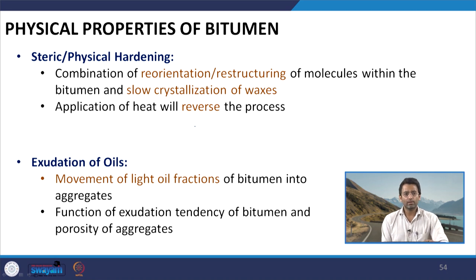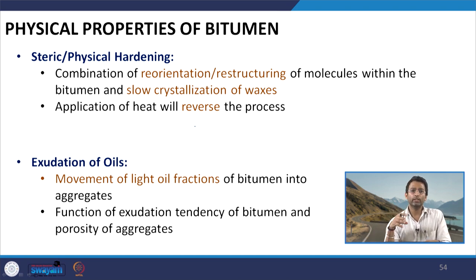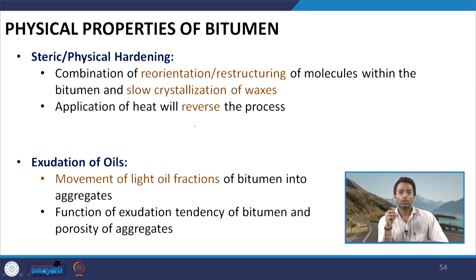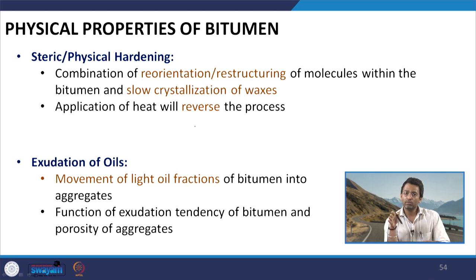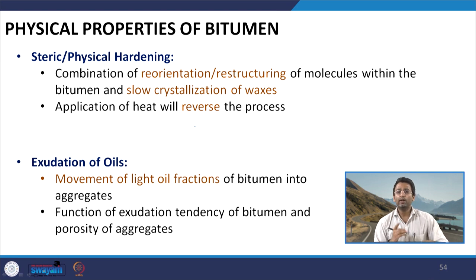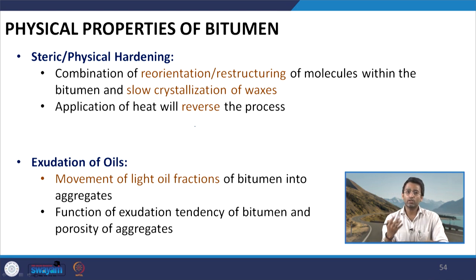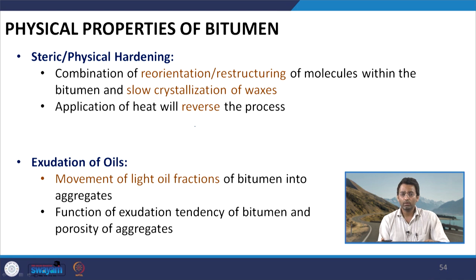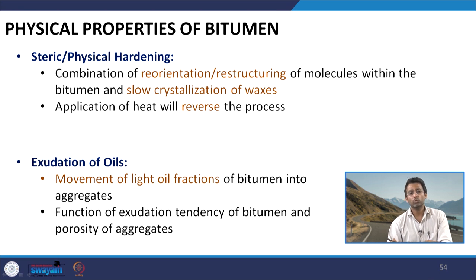The last factor is exudation of oils. Lighter oil fractions within the bitumen may seep inside aggregate pores. This depends on the exudation tendency of the bitumen and the porosity of the aggregates — higher porosity increases the chances of oil exudation. Out of all factors discussed, oxidation of bitumen is the most critical and important factor contributing to aging.